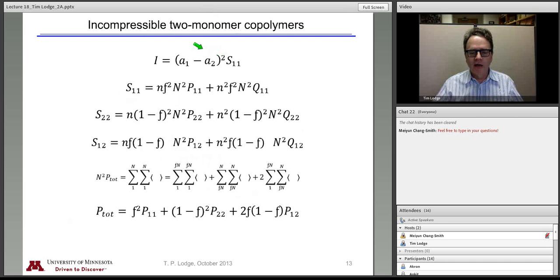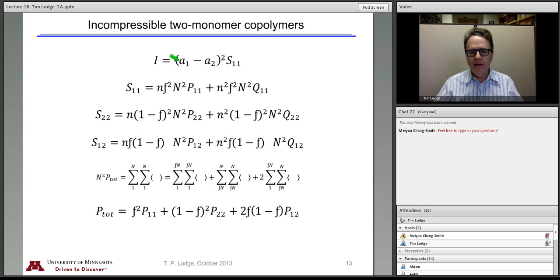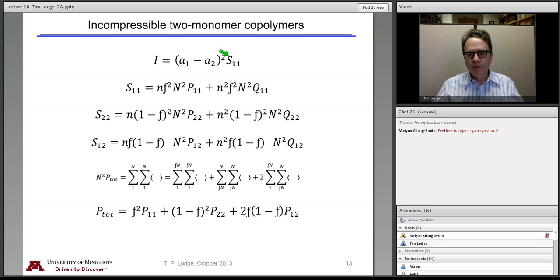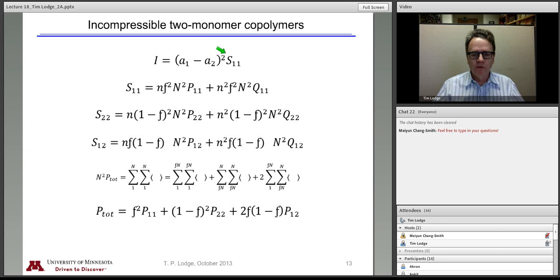This is not going to be as bad as it looks. I'll remind you of this top equation — if we have a two-monomer system and it's incompressible, the scattered intensity is given by the difference in the scattering lengths of the components squared and the partial structure factor S₁₁, which tells you about the spatial correlations between all of the monomers of type one. The incompressibility assumption was that every place in the sample is either monomer one or monomer two, so if you know where ones are, you know where the twos are and you know all the correlations.